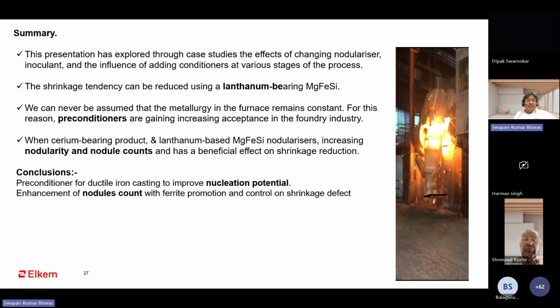So in conclusion, preconditioner for ductile iron is important to improve the nucleation potential. It is the same for gray iron also. Enhancement of nodule count will help to get more ferrite content and control micro shrinkage. This is the benefit, so increased nodule count is a lot of benefit. Also, it will help to improve machinability. More graphite precipitation, either flake or nodules, gives better machinability. So you have to select the combination that helps to precipitate more graphite, either flake or nodules. So this is for ductile iron, a high performing package combination that helps to improve the yield.